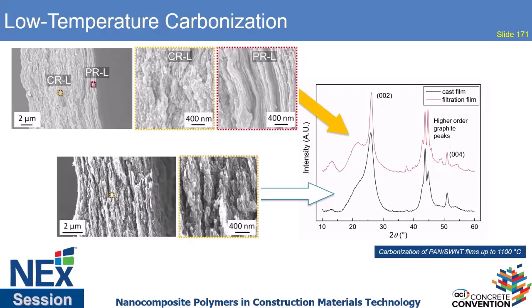But this is that two-layer film that I showed you earlier, where I know one side of the film has really nicely blended polymer phase with the nanomaterial, and the other side is those rejected nanotubes that are just kind of existing. So we kept track of those sides, treated it the same, and you can see very clearly here the graphitic layered structure. So at 1100 degrees, I'm forming almost a very perfect hexagonal layered X-ray structure. I'm getting that extra rhombohedral coming from this layer, and in a case where I don't control this phase separation, it's all intermingled, so you can kind of see that.